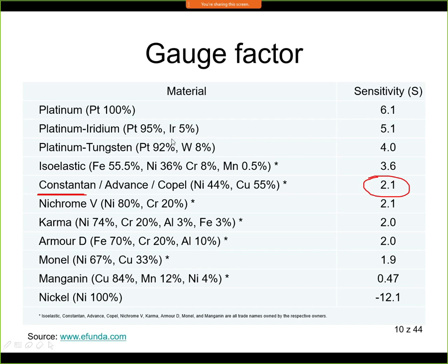And one of those materials is constantan. Constantan is an alloy of copper and nickel. Here you can see the composition, so 55% copper and 44% nickel. And the sensitivity, the gauge factor, is 2.1. It varies a little bit with the composition, so if the composition is different, then the strain gauge coefficient, the gauge factor, will be different as well. But we can say that the gauge factor of metallic strain gauges is approximately 2.